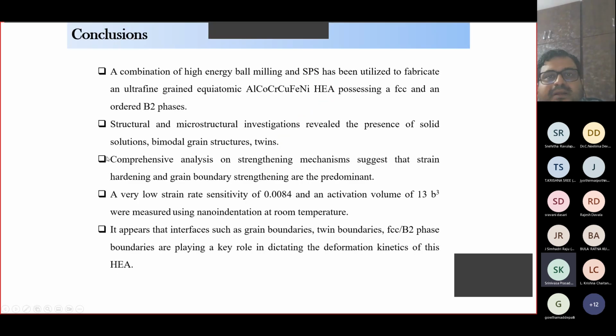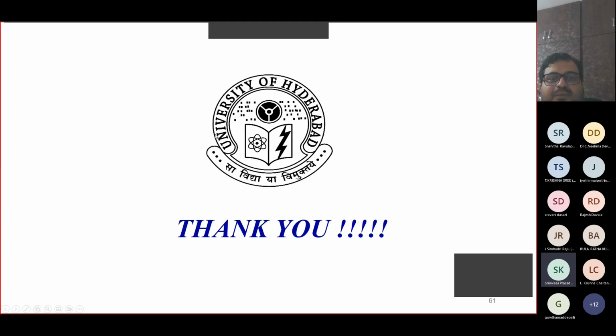A combination of high energy ball milling and spark plasma sintering has been utilized to fabricate an ultra-fine grained material. If the average grain size is less than 100 nanometers, you call it a nanostructured material. If the grain size is above 100 nanometers and below 1 micron, that is 1000 nanometers, you call that ultra-fine grained material. Above 1000 nanometers, which is 1 micron, you call them microcrystalline materials. Structural and microstructural investigations reveal the presence of solid solutions, bimodal grain structures, twins, and so on. A comprehensive analysis of strengthening mechanisms was done, and we have observed a very low strain rate sensitivity with a low activation volume. Interfaces such as grain boundaries, twin boundaries, and phase boundaries play a key role in dictating the deformation kinetics of this high entropy alloy.